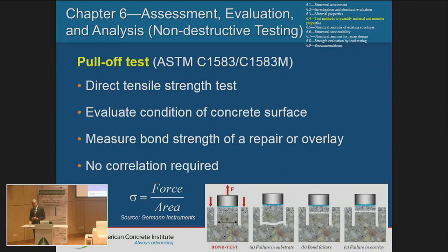Pull-off test. That is one of the most used methods to test overlays. If you have an overlay, you get what you call the direct tensile strength. You have this cylinder that you adhere to the concrete, then you drill around it, and then you pull. You'd like to have your failure within the substrate, which is the existing concrete. If you get your failure within the interface, that means you don't have good bond, not necessarily, but most of the time. So you'd like to have the failure either in the new overlay or in the existing concrete, but not in the interface between the two concretes.